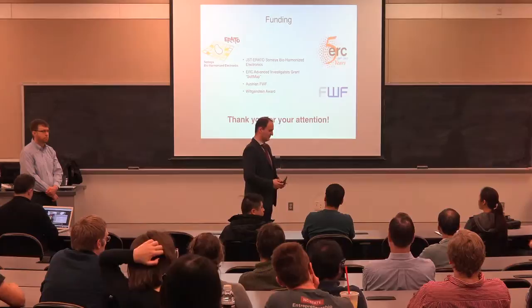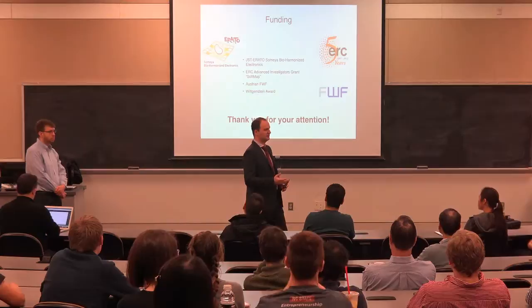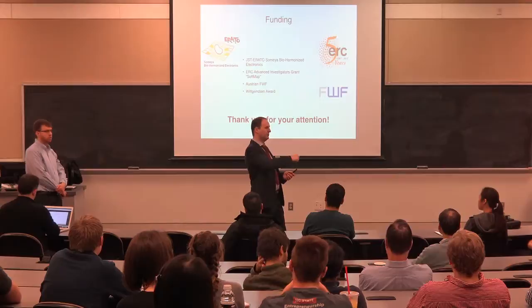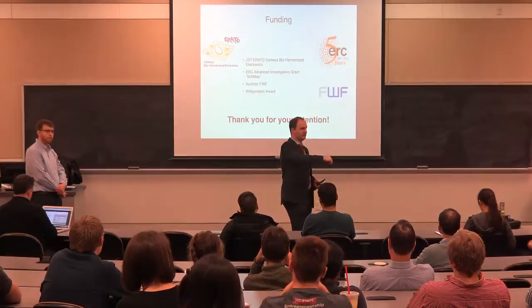Liquid metal is good. What we are using now are also indium-based soldering pastes, materials where you can work in the reflow process at maybe 60, 70 degrees centigrade. This is what we use, for example, for the on-screen demonstrator to connect the 1 micron foil to the actual readout electronics. We just screen print and apply low temperature soldering paste. So that's maybe one way. People use anisotropically conducting pastes. It's very successful to combine this.